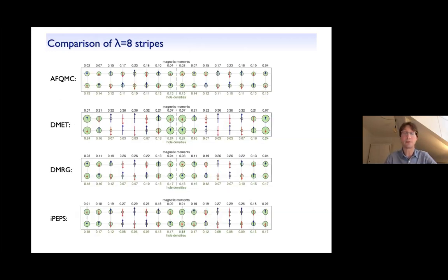Then we can also compare the different order parameters of the stripes. And now you can clearly see differences on the quantitative level. So typically the stripe order from auxiliary field quantum Monte Carlo is weaker than found in DMET, for example. But on the qualitative level, all these approaches reproduce similar features, like the pi phase shift in the antiferromagnetic order, or for example, the absence of superconductivity in these results for this stripe.